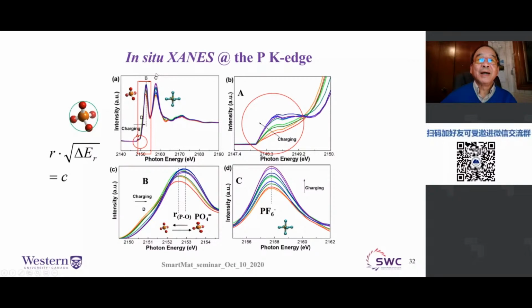Okay, so if you look at the phosphorus K-edge spectrum, you have this peak and you have this peak. Now let me talk about this peak. This is peak C, which is from the electrolyte, which is hexafluorophosphate. It doesn't change because of the electrolyte itself. But the phosphorus A and B are actually features from the electrode, and you can see this resonance changes, okay, as lithium goes in and out, right?